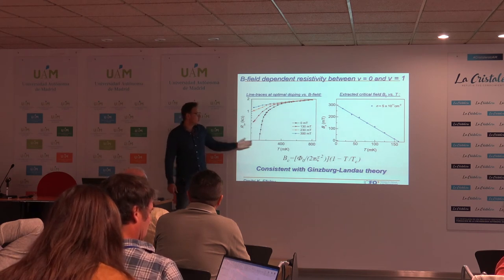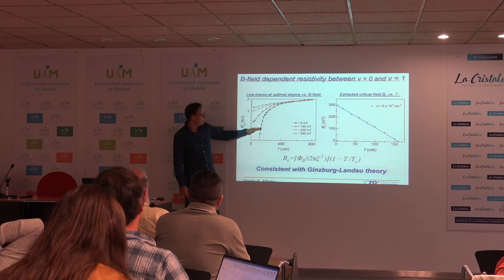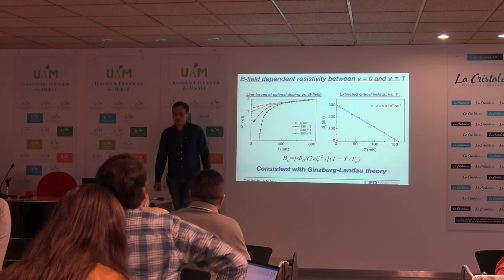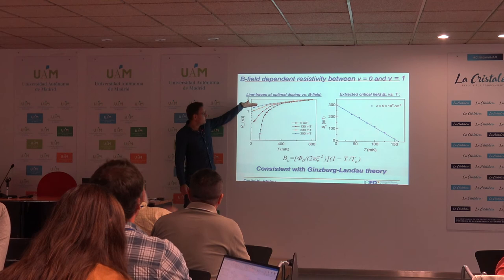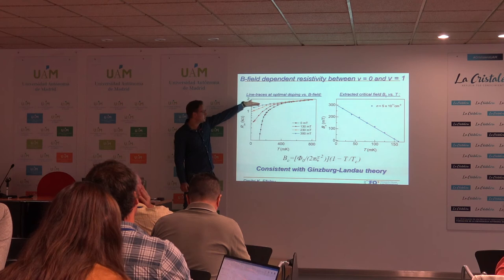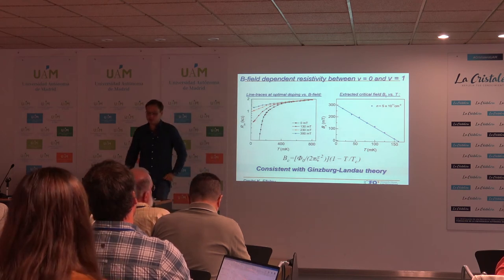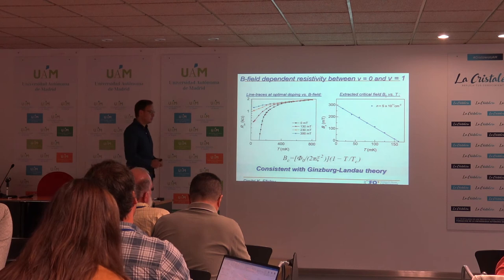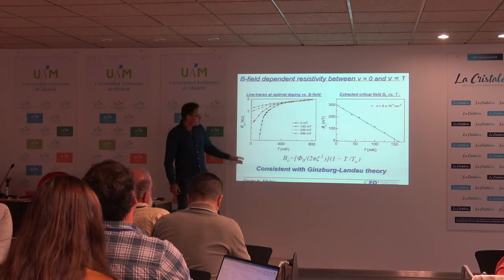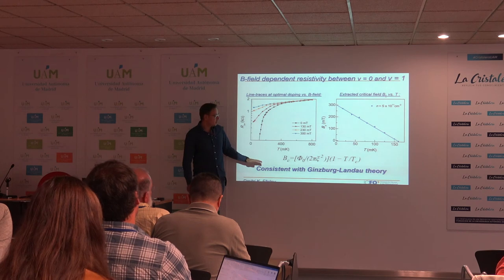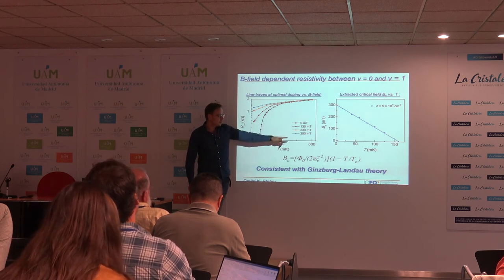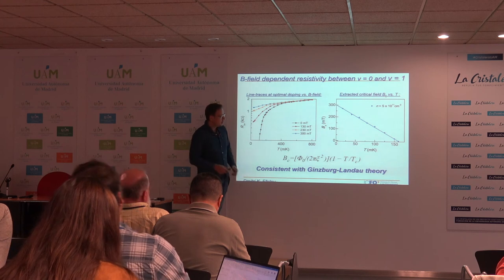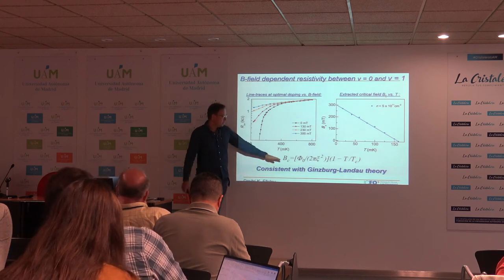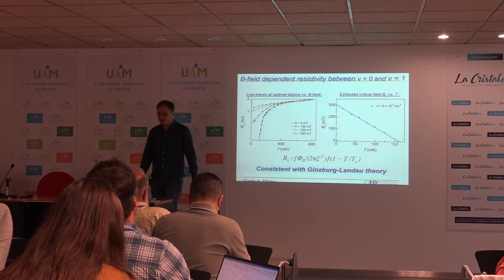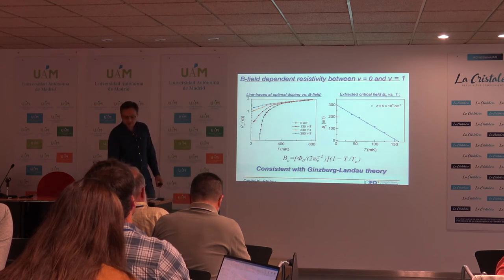So this is resistance as a function of temperature. And then we apply a magnetic field, and really these superconductors are killed. And above 300 millitesla we recover again this linear temperature dependence. So in principle, this linear temperature dependence continues to go to even lower temperatures, to even like 10 millikelvin or so. Then, of course, from this data we can extract the critical magnetic field, and we can plot it out as a function of temperature, so this is right here. And we again get a similar behavior as in the previous work, where we can fit our system to the Ginzburg-Landau field.